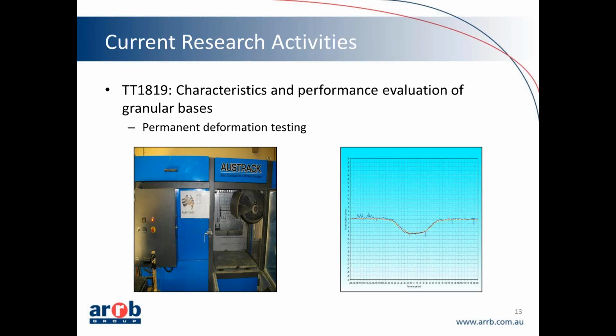So you can see here, this is a picture on the left-hand side of the Austrack. What we can do here is compact and track pavement samples. At the moment we're doing unbound pavement materials. The sample size that we're producing weighs roughly between 200 and 300 kilos, and the sample is around about 300 millimetres deep. So we do the compaction part of it. What you can see in that picture is the tracking mode, and on the right-hand side you can see a laser profile of the rutting of the particular sample that we tested. It's a pretty fancy bit of gear that uses a laser profiler to establish the initial surface, and then we measure the rut depth at various different locations and times.